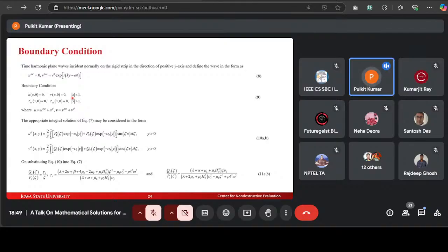So you know the strip is rigid, so the displacement component will be 0 at the strip location, and the total displacement field is defined by u equals u incident plus u diffracted, and v equals v incident plus v, the diffracted part of the wave. And here I have removed the time factor, which is common in all the variables. So what is the diffracted displacement? The diffracted displacement refers to the displacement field of a wave after it encounters an obstacle such as a crack or a strip, causing wave scattering and diffraction.